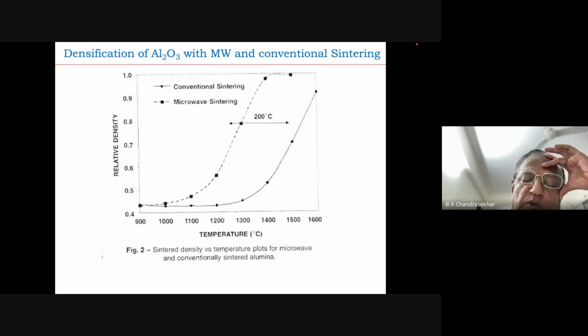It has to be done very slowly, and the sample also has to be heated very slowly, because you don't want too much of a differential thermal gradient between the center of the sample and the surface of the sample, which is exposed to the heating elements. Typically, depending upon the size of the sample, it will take 1 to 2 hours.